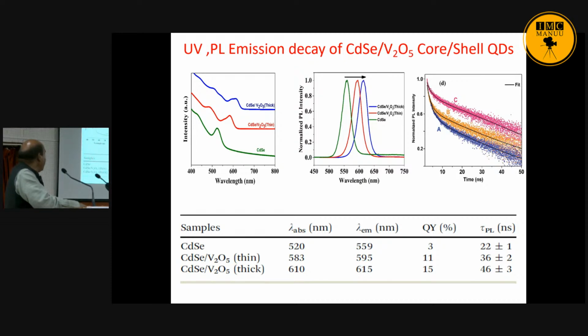If you see the quantum yield, it is only 3 for CdSe. But if you take CdSe/V2O5, the quantum yield increases to 11 and 15, and time decay also increases here. So we can say this quantum dot is stable as well, and the quantum yield also increases. So this is optically applicable too. This is the conclusion of this study.